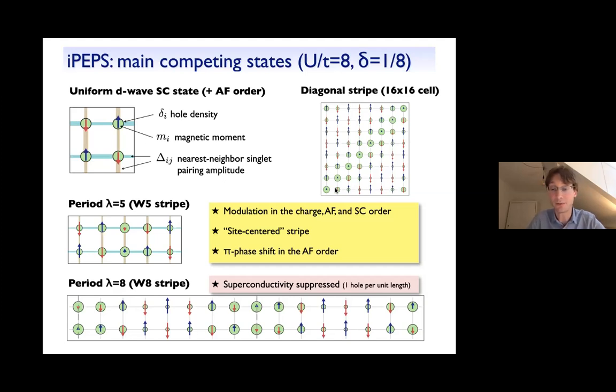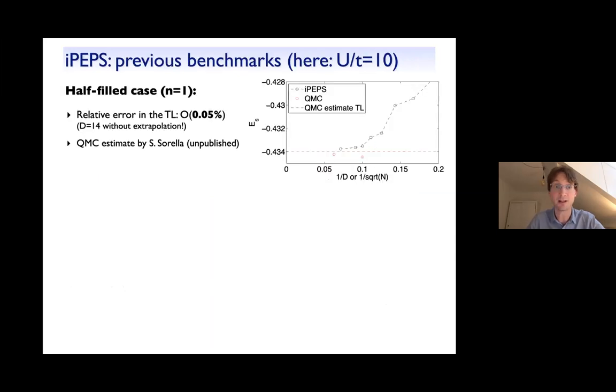Now, before coming to that, let me show you some other previous benchmarks to get a bit of an idea what the main challenge is here. So first, I show you a benchmark at half filling. At half filling, there's no sign problem, so we can directly compare with quantum Monte Carlo. So that's the energy per site as a function of 1 over the bond dimension. You can see here how the variational energy improves as we increase the bond dimension. And then down here, this is data from quantum Monte Carlo for different system sizes. And the dashed line is the quantum Monte Carlo result extrapolated to the thermodynamic limit. So you can see in the end here, we are similarly close to the thermodynamic limit as the last Monte Carlo point here, and we obtain a high accuracy even without extrapolating.